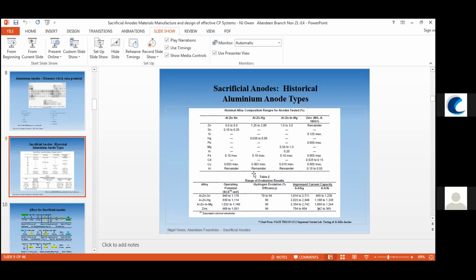The mercury is an obvious one in that whilst it had a beautifully high ampere hours per kilo, it's a toxic material, and it fell out of favor and was not able to be used environmentally, and so those have literally been banned. We're now using the favored aluminium zinc indium based system, along with our traditional zinc materials, which was developed into a military zinc, which contains aluminium and cadmium as its main additions and activators.